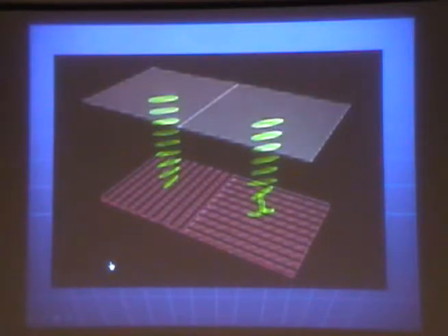And there occurs a buckling of the orientation. So this is an intermediate state where you're seeing the buckling of the surface, changing the orientation abruptly from this direction, with the arrow pointing this way, to the opposite orientation. The arrow is pointing this way. And this is the relaxation to reduce the twist energy.